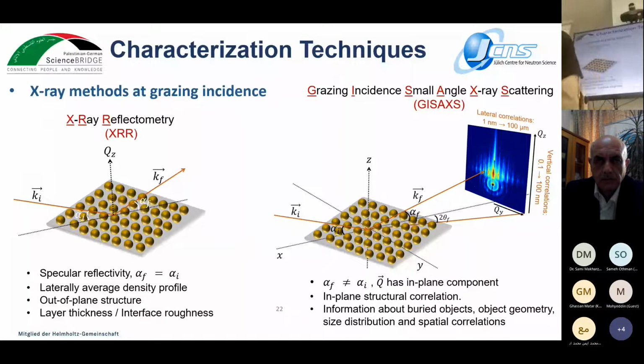We have an incident X-ray beam with k initial directed toward the sample surface. In the case of X-ray reflectometry, the beam is scattered at a scattering angle equal to the incident angle, and we collect information as a function of the z component. While in GISAXS, the incident beam is scattered along k final with a scattered angle alpha f and 2 theta f.